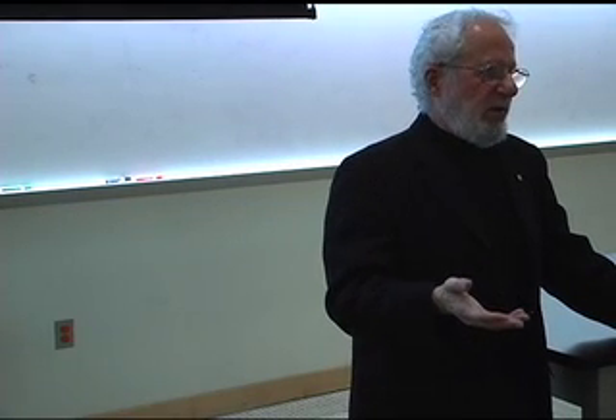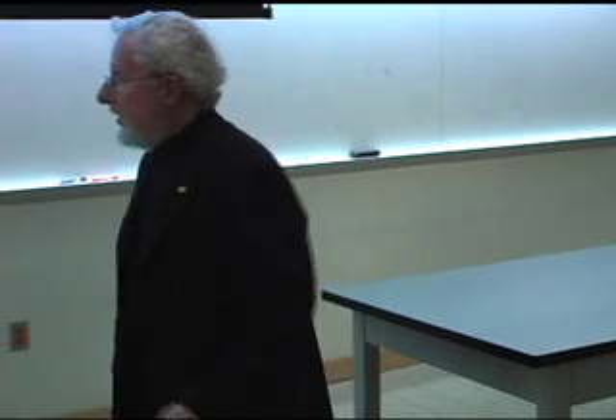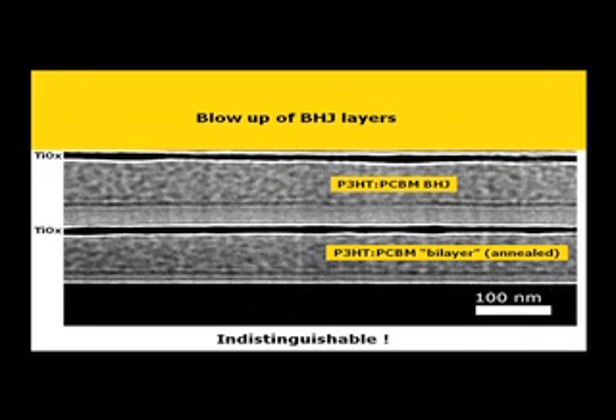And there's another way you can try to do it. You cast one film of one material, then you put the other film on top of it using a solvent which is not a solvent for the first. And then you anneal it, let things happen. And the answer is exactly the same nanostructure, whichever way you form them. See in more detail there.